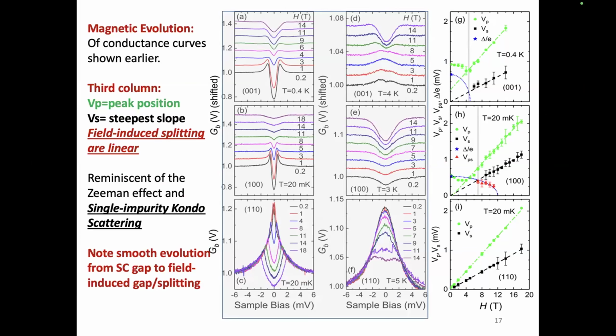So these are just plots, okay, to show you that the green is that splitting, at the higher temperature and the lower temperature. These are all fits to show that we can map out the order parameter. So this is just really to show that, I'm sorry, I said the wrong thing. This is the peak to peak position of that splitting. And the black is what you call steepest slope.